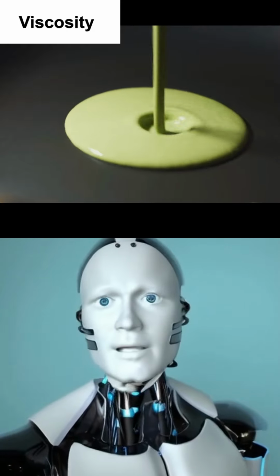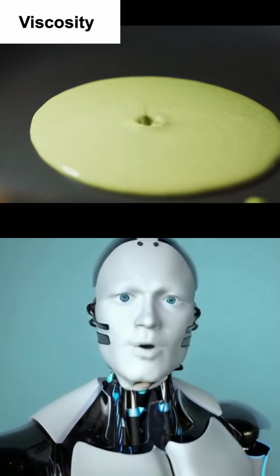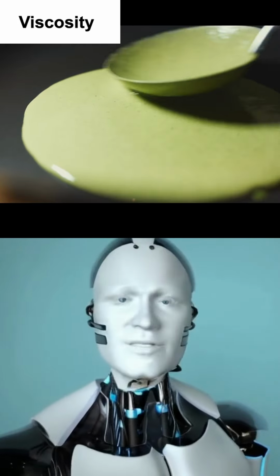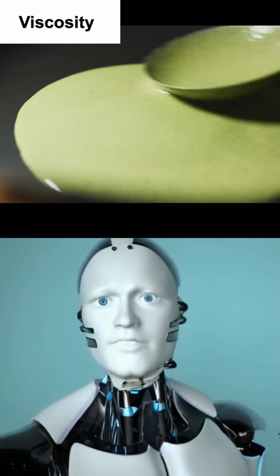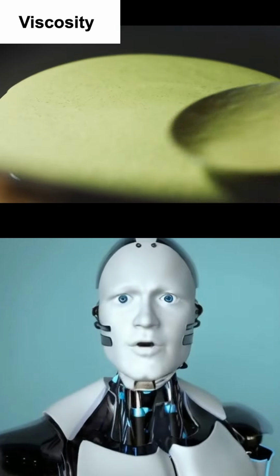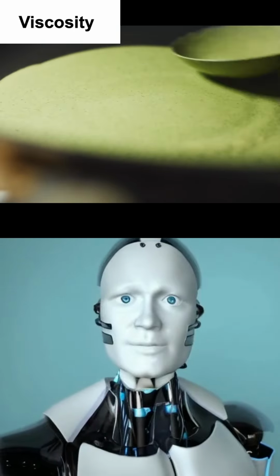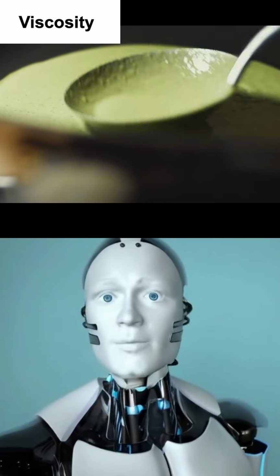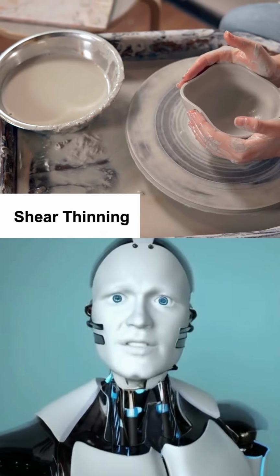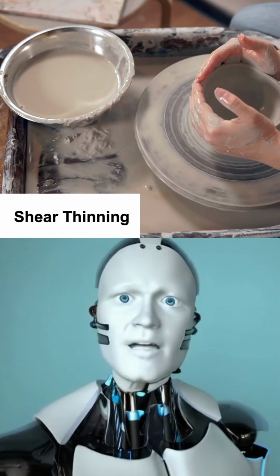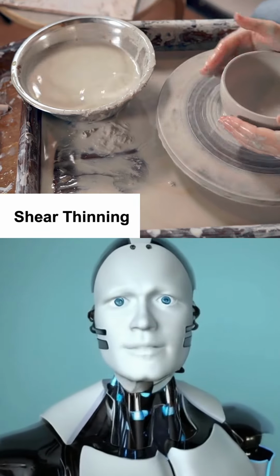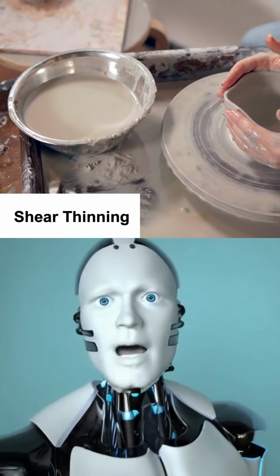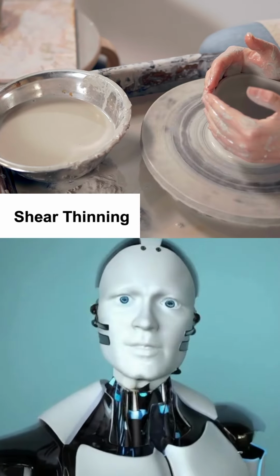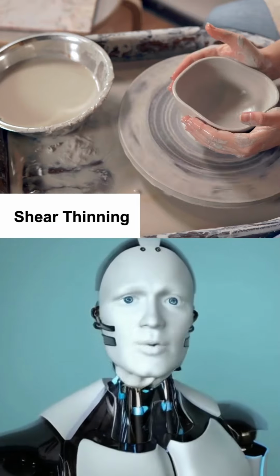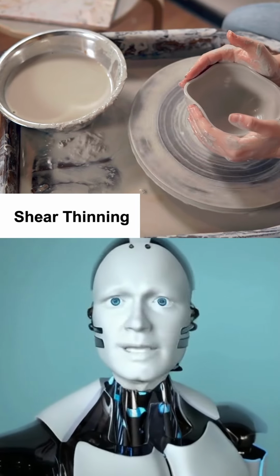Rheology helps determine factors like extrusion, shape fidelity, and printability. One of the primary properties is viscosity, or the resistance of a fluid to flow. Too high of a viscosity can lead to nozzle clogging, but too low of a viscosity can lead to poor shape retention. Another important property is whether or not a material exhibits shear thinning, or the decrease in viscosity as the shear rate increases. In other words, when a high-pressure force is applied to a shear-thinning material in the nozzle, its viscosity will decrease, allowing it to flow more easily.